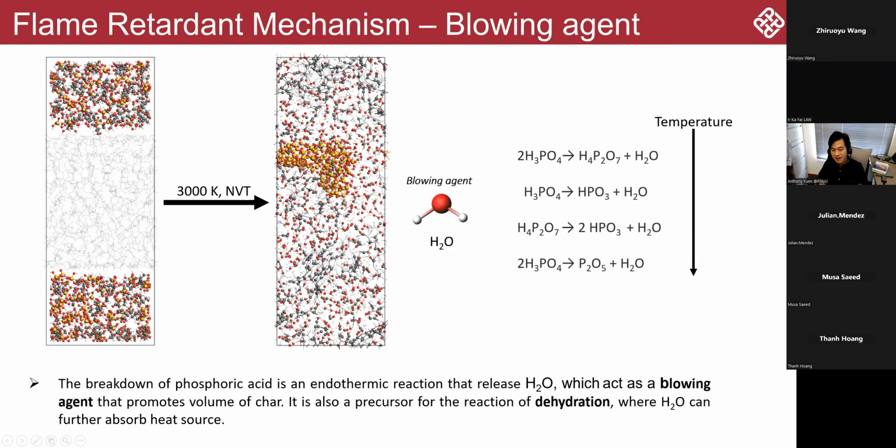But if you look into this case alone, the powerful thing about MD is we can even identify the so-called chemical pathway of the products. So, for argument's sake, let's specifically look at all the phosphorus-based reactions. We can see that it will form phosphorus because of the phytic acid content. The phosphorus itself is a recirculating reaction.